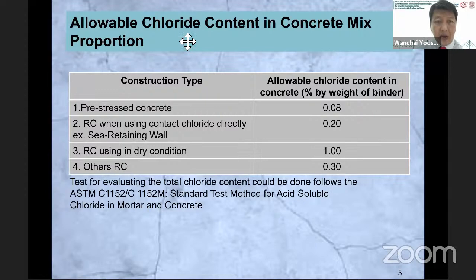It is about the allowable chloride content in concrete mix proportion. This allowable chloride content depends on the construction type. For pre-stressed concrete, we have an allowable chloride content of only 0.08% by weight of binder. For RC structures in direct contact with chloride, for example a retaining wall, we have an allowable chloride content of 0.2%. For RC used in dry condition, we have an allowable chloride content of 1%, and for other RC it is 0.3%.